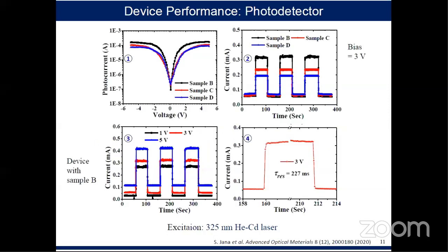In this slide, I have shown the different device performance of different nanocrystal samples. From figure 1, we can see the photocurrent of the various devices using sample B, C, and D. As you can clearly see, sample B has the highest photocurrent, and sample D has the lowest photocurrent. That is because sample D contains lots of surface traps, so they recombine the photo generated electrons and holes. So that's why the photocurrent is very less. From figure 2, we can also clearly see the temporal modulation of the various devices. Sample B has shown the highest modulation index, that is due to its highest photocurrent.